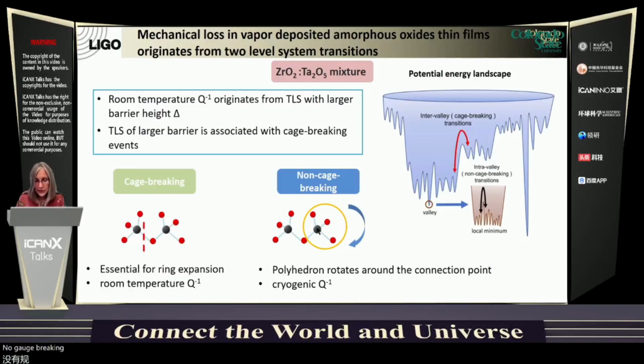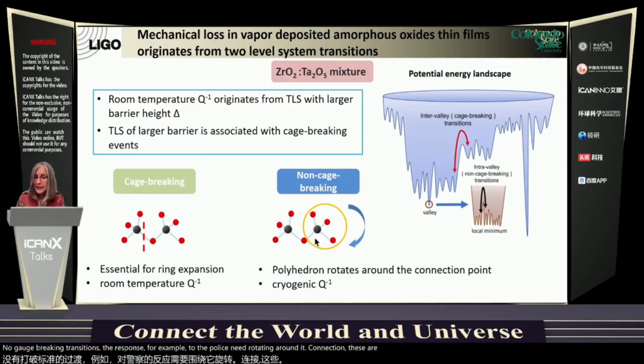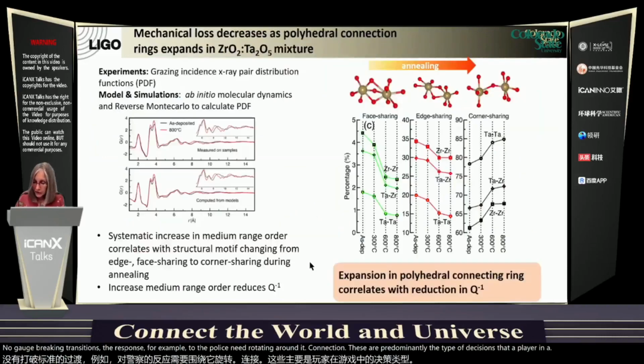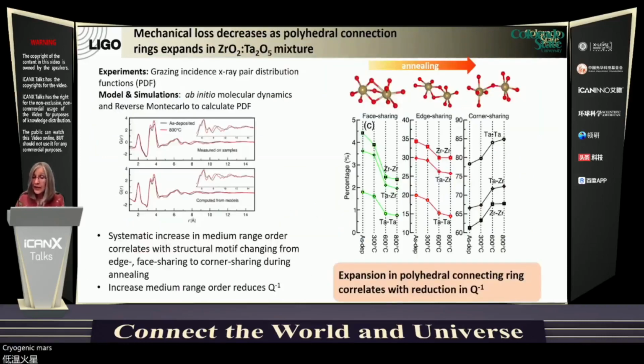Non-cage breaking transitions correspond, for example, to the polyhedron rotating around a connection. These are predominantly the type of transitions that occur in cryogenic loss that is detrimental in affecting coherence in superconducting quantum bits. Coupled to this work, Kiran Prasad from Martin Fejer's group at Stanford, in collaboration with us, showed in experiments and simulations that in zirconia tantala, the reduction in mechanical loss is associated with an expansion in the polyhedral connection that is schematically shown here.